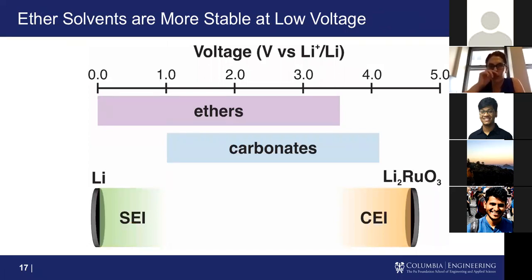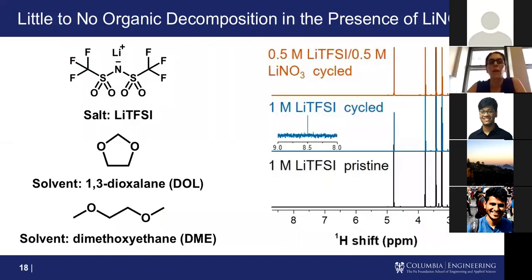Again, you'll remember, in general, the solvent should be very stable, especially compared to the carbonates. So we wouldn't necessarily expect the solvent to decompose. It might be that the salt itself is playing a more important role here, especially since we see big changes whenever we add a different salt in. So if we take a look at our proton NMR, this is just showing changes in decomposition of the ether molecules after extended electrochemical cycling. What we see if we compare to the pristine mixture is that we don't really see very much decomposition in the ethers. And that's pretty consistent with what we would expect given the electrochemical stability.